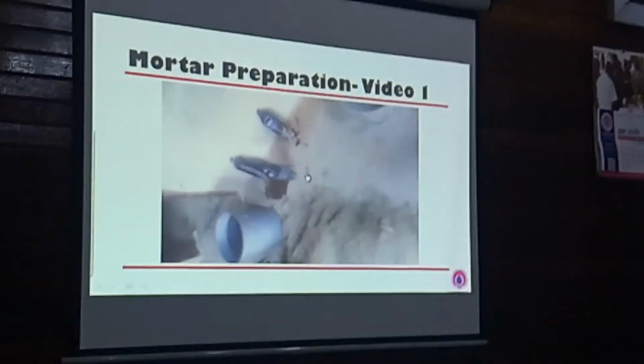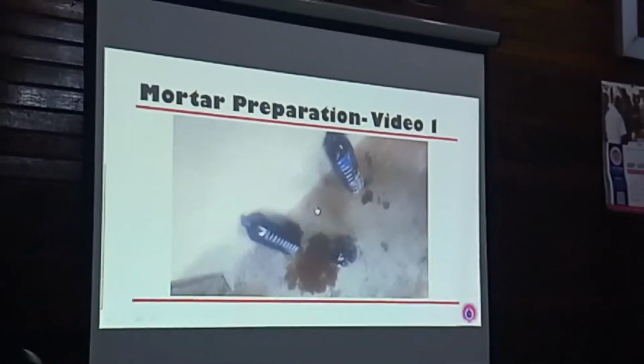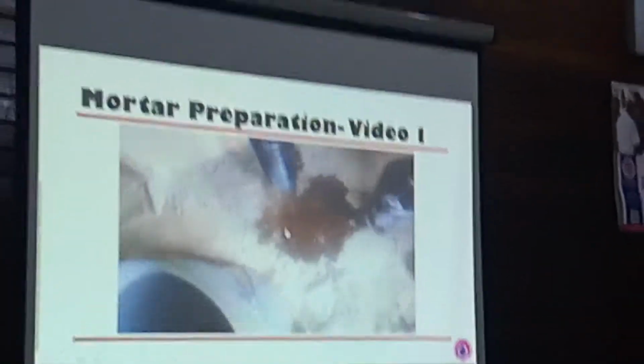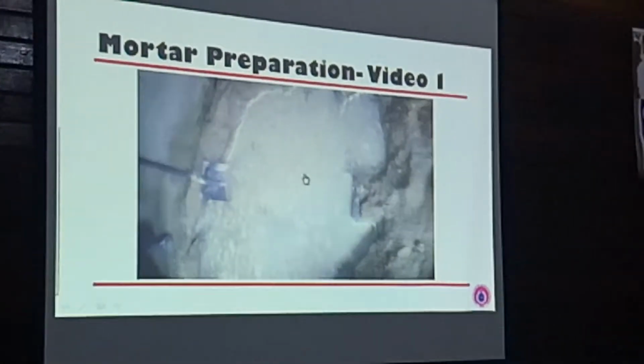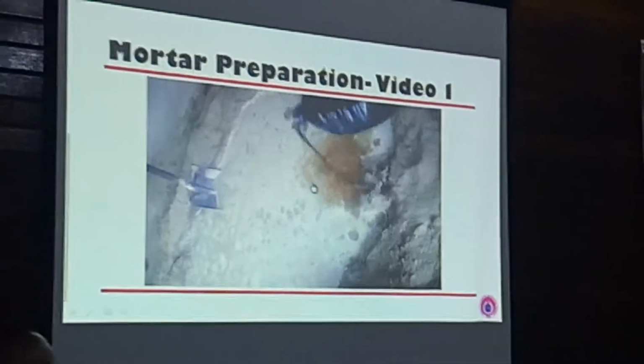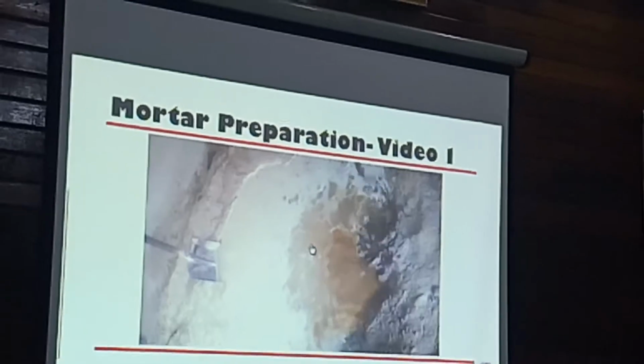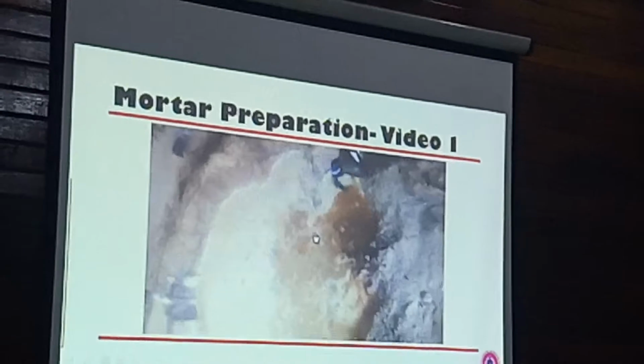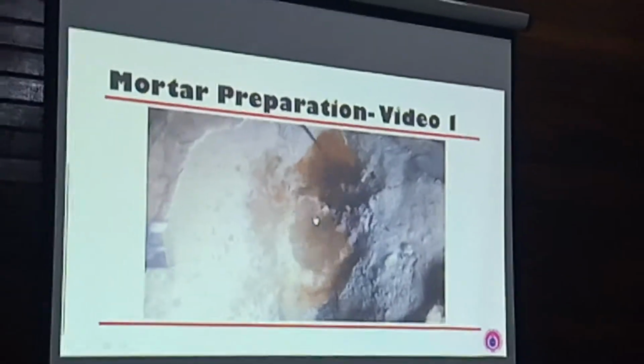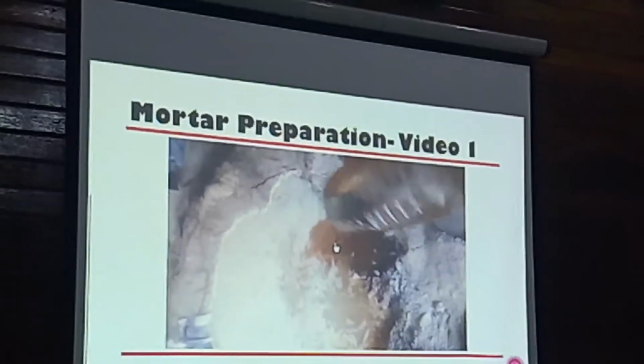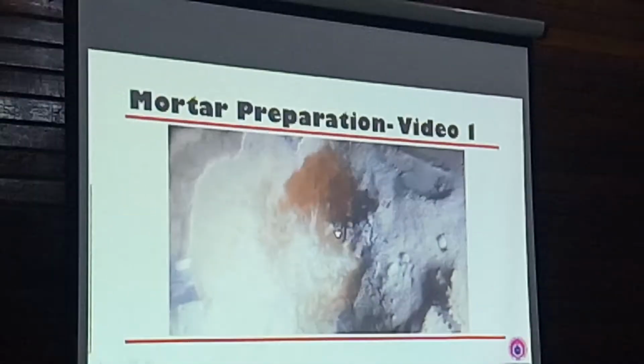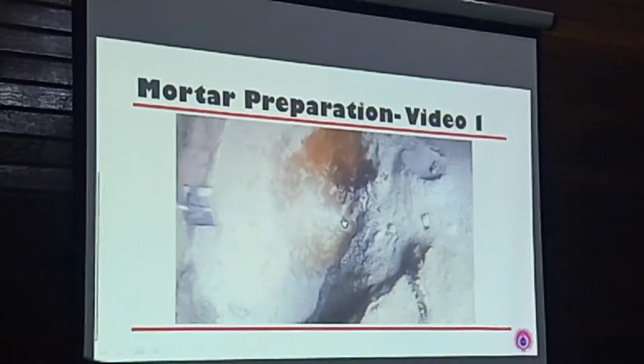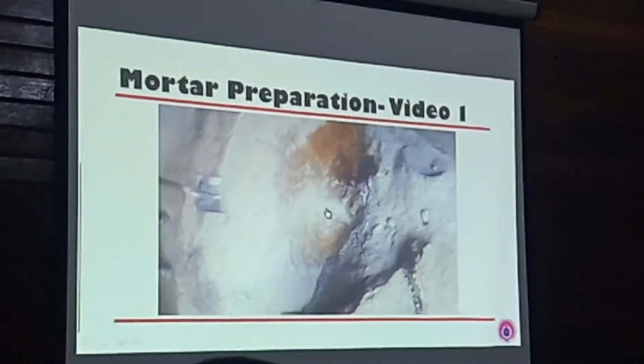Okay, so this is field work. There, I tried to do all these mixes for them, and they formulated everything, the mortar, the sand, and then the pozzolan. What I did was that because I knew that 40% was okay, I contacted the factory manager and I formulated 40-60% of the pozzolan cement from the factory. And then I sent it to the field. So they are pouring the chemical admixture into it. The chemical admixture, I tell you, is the game changer. It changes a whole lot of things. Yeah, so this is how it was applied.